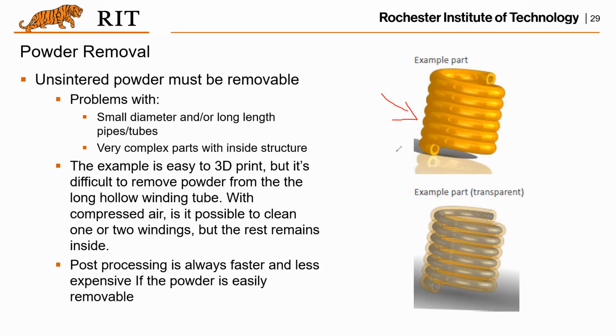And if you do not have an opening, then that means it's really hard to remove the powder during the printing process. Actually, that is a similar problem for the stereolithography process. In stereolithography, if you're not aware of your design, there could be cases where the liquid material is trapped in a volume. That happens if you do not have an opening. That is the exact same case as what we have for the powder-based ones. If we do not have an opening to let the powder go out, there could be some powder remaining in those internal spaces of your part.